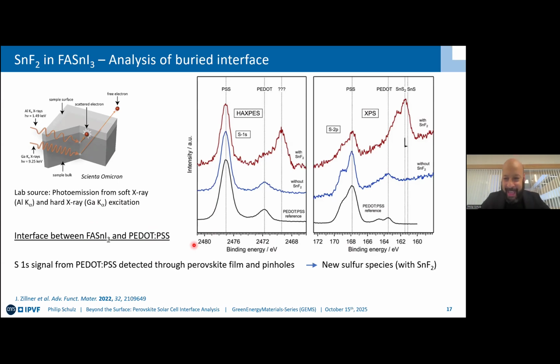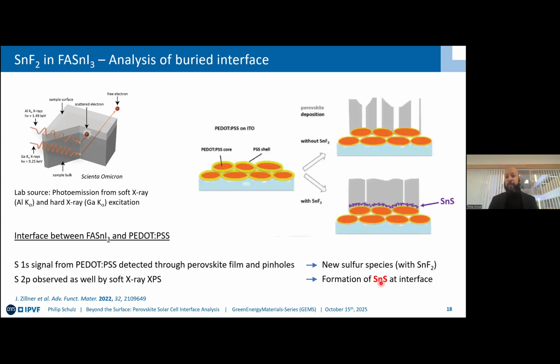So, XPS versus HAXPES of this particular interface system. What is not shown here on the slide is that PEDOT has a thiophene unit, whereas PSS has a sulfonate, and these show in distinct sulfur core levels here, probed by HAXPES and also probed by XPS. What you can then see is once you add also tin fluoride, you get these additional peaks. And these new sulfur species actually correspond to tin sulfide at the interface. So this was something we did not expect, but once you introduce this tin fluoride, you inadvertently get tin sulfide, but only if you have a sulfur source in your substrate.